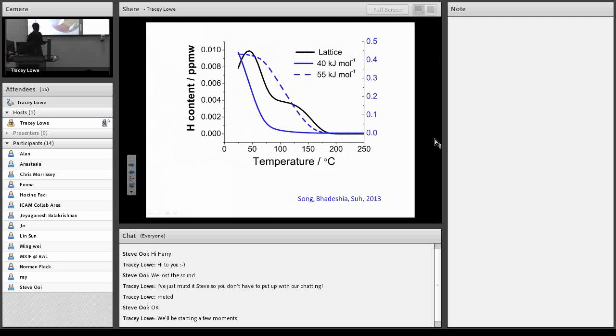So we have been working on this theory, and we have just published a paper on the analysis of TDA curves. And you can see that peak shapes will depend on the distribution of activation energies that we have in the traps. And we hope to use this theory now to examine in more detail the spectra that we get from TDA, thermal desorption analysis. This is, of course, a numerical model, because as soon as you get to more complexity, it's difficult to express things analytically. It's much easier to do it numerically. And the computer programs for this are available on our website.